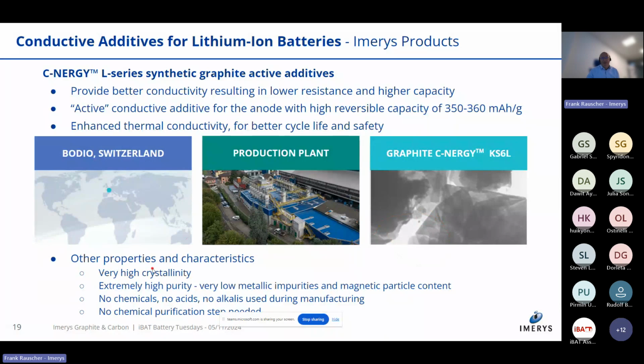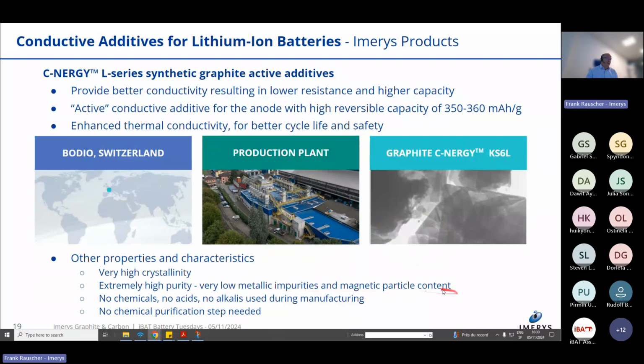Because of the specific process that we apply, a high temperature process, close to 3000 C, we achieve very, very high purities. Basically, the temperature that we apply drives out impurity. We end up with very, very high purity materials where we have single-digit ppm levels of impurities, and that's also what the market needs and is asking for. Very low metallic magnetic particle content. We don't have to do any washing or any purification. The way it comes out of the process, of course, we mill it down, we condition it, we fraction it. We have different fractions. We may do a surface modification, but then we can sell. We don't have to have a chemical purification step.